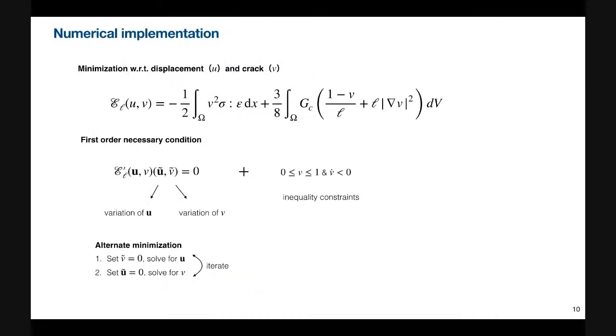So here I will talk a little bit about how we numerically implement this minimization problem. This is our implementation. It's not the only way to implement it. There are some other ways, but we look at the first order necessary condition for the energy functional to be a minimum. So we take the directional derivatives and set them to zero with inequality constraints. The inequality constraints are that the phase field variable v has to be bounded between zero and one, and that its evolution should be strictly negative because of the irreversibility.